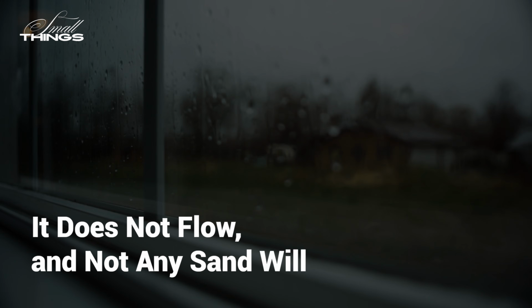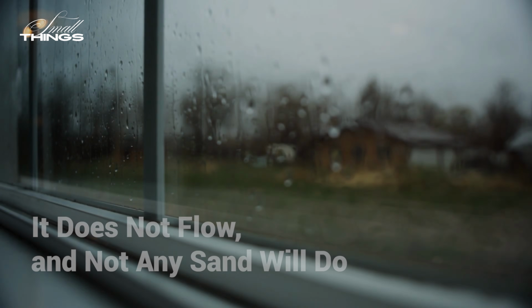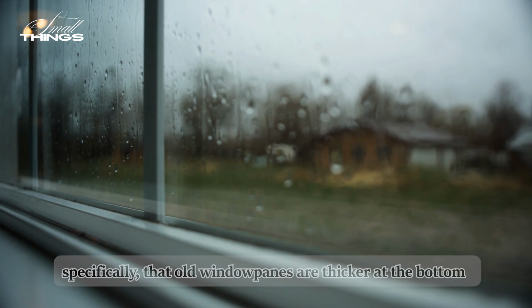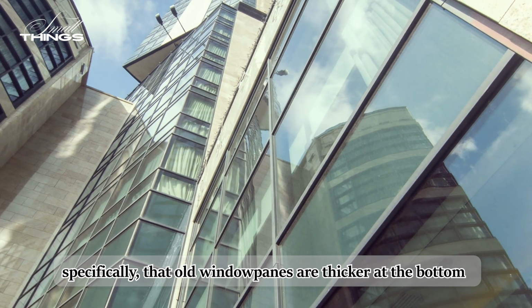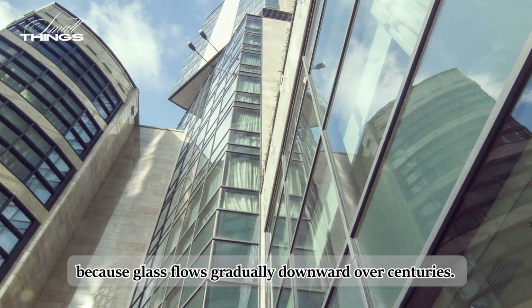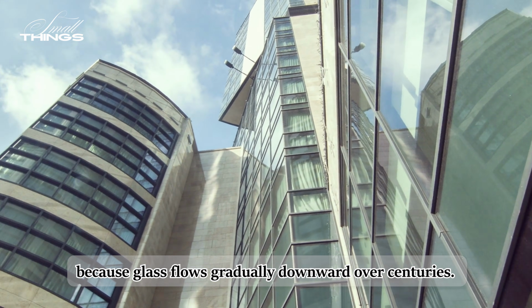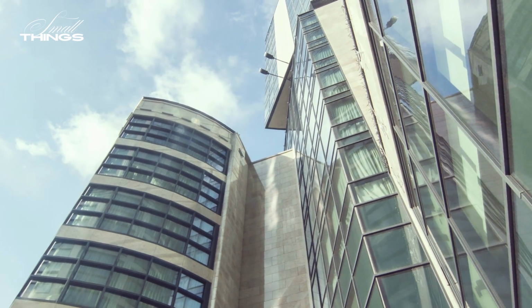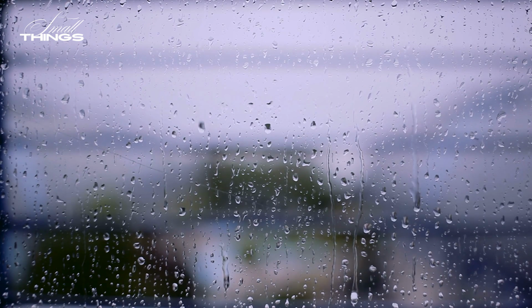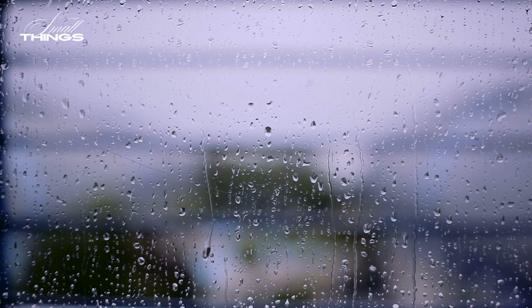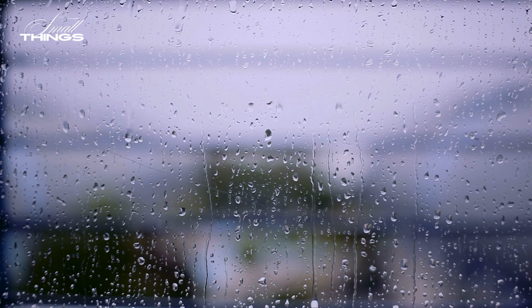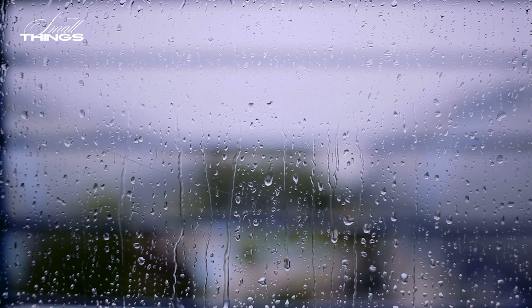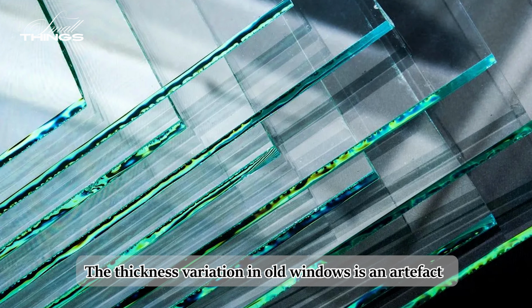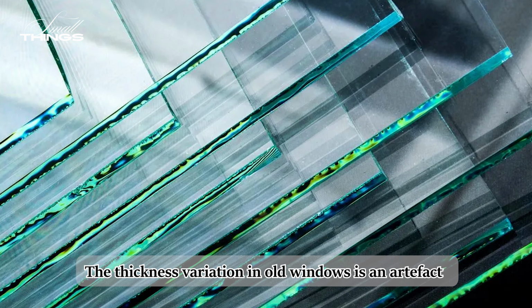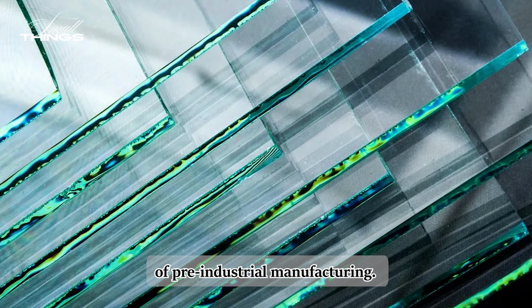It does not flow, and not any sand will do. The most common assumption about glass is that it is a slow-moving liquid, specifically, that old window panes are thicker at the bottom because glass flows gradually downward over centuries. That is wrong. Glass is a solid. Its atoms are randomly arranged rather than crystalline, which gives it some unusual properties, but it does not flow at room temperature. The thickness variation in old windows is an artifact of pre-industrial manufacturing.